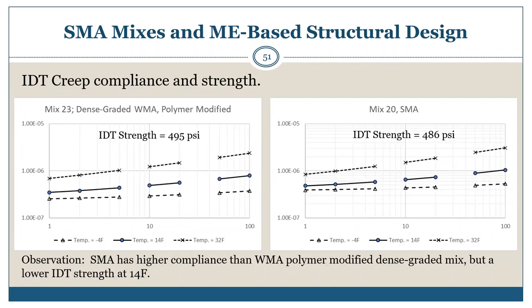This slide shows the indirect tensile creep compliance and strength values. The graph on the left is for mix 23 for dense graded polymer modified warm mix asphalt. The graph on the right, mix 20, is the test results for an SMA.